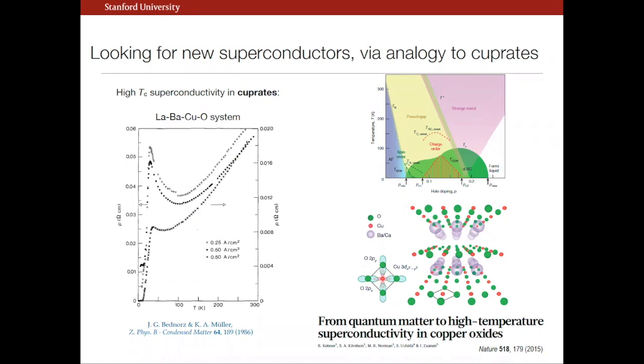And so I won't go through all of this in detail, but just to refer you mentally that there is a dome of superconductivity. It's proximate to an antiferromagnetic Mott insulator, and the endpoint in the overdoped regime is commonly understood to be a Fermi-liquid metallic endpoint. And the common structural feature, of course, is the copper oxide planes that in the hundreds of different structural manifestations is a common unit. Okay, so, and again, this is very much tying in then to yesterday's discussion.